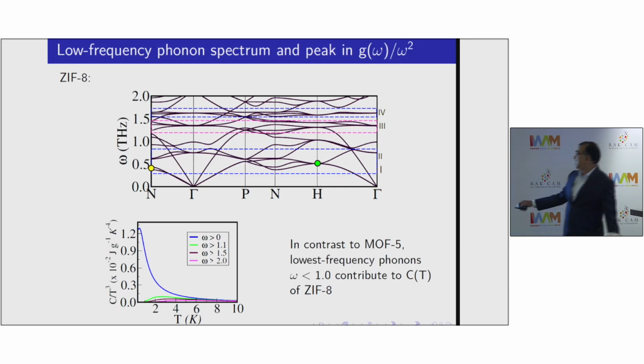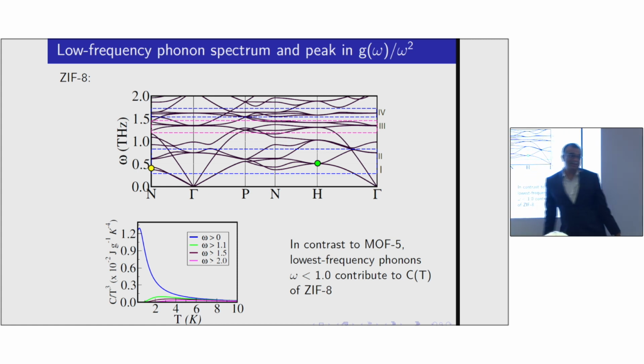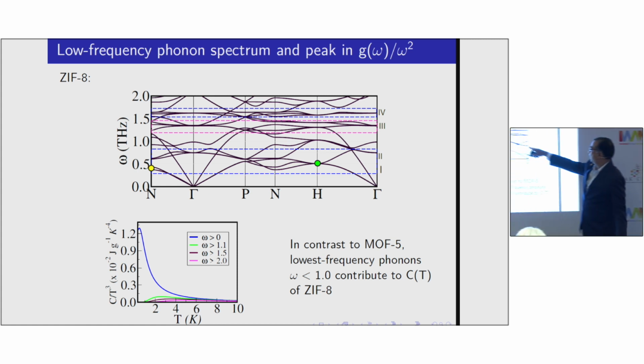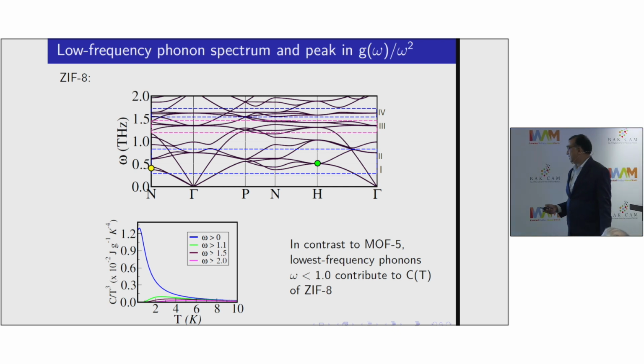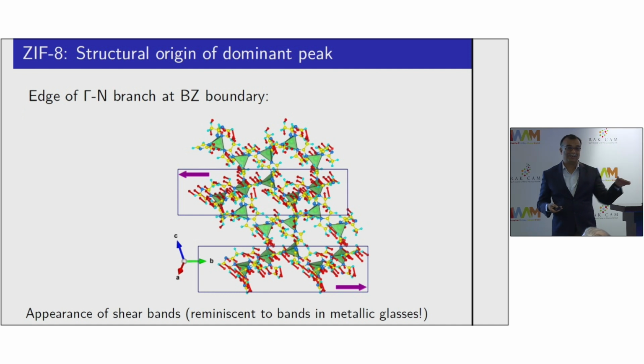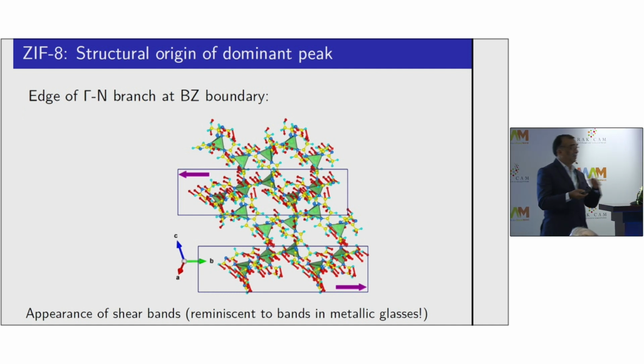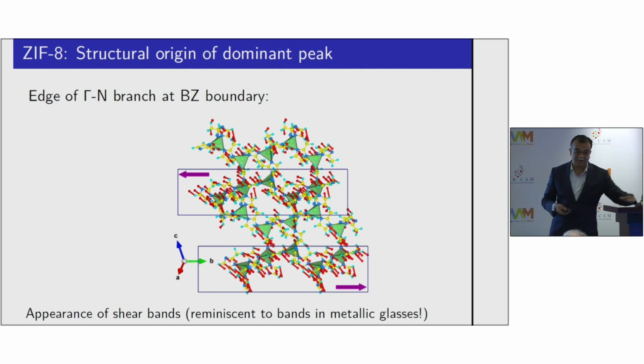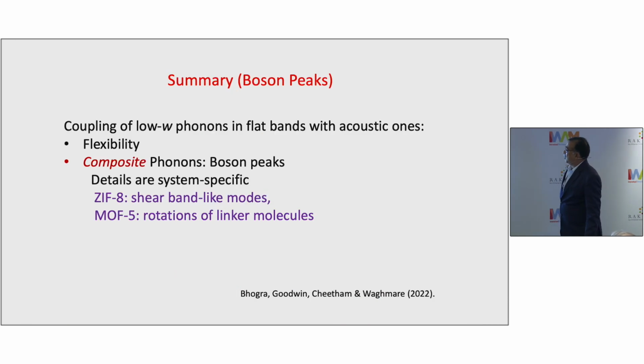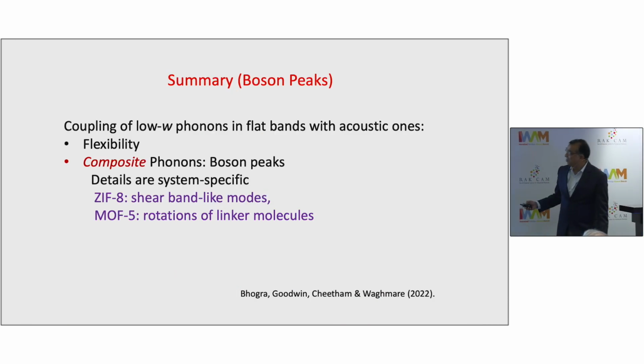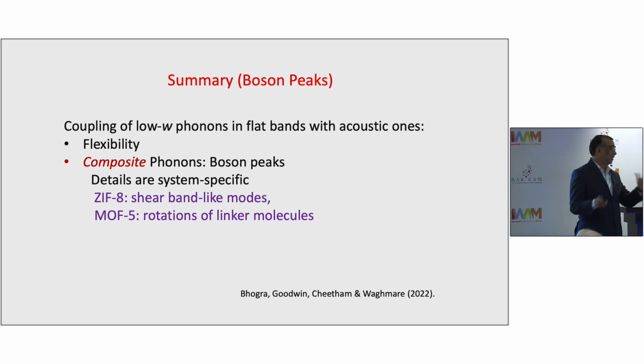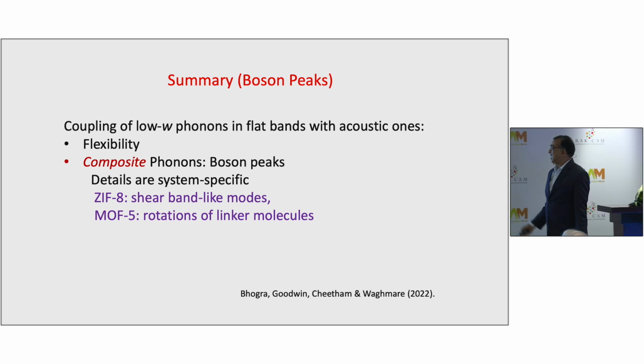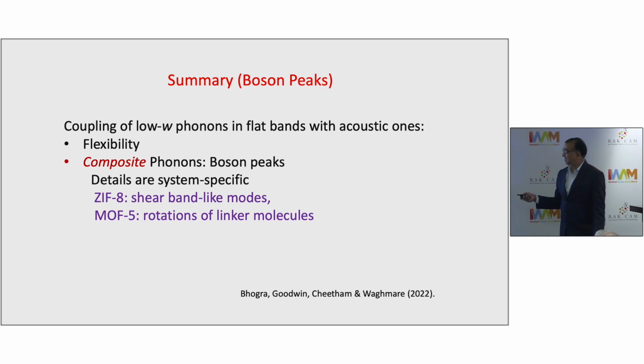In ZIF8, again, there's only one set of phonons which dominates the boson peak. And that set of phonons is indicated here in this window. And basically, those phonons involve shear band-like distortions. And again, this is something which is known in amorphous systems. They deform in response to external stresses by forming shear band-type structures. So let me summarize. It's the coupling between low-frequency optical phonons in flat bands with acoustic ones that gives rise to both flexibility and composite phonons. Meaning phonons are a combination of strain and internal strain waves. And the details are system specific. In ZIF8, these arise from shear band-like modes, whereas in MOF5, they involve rotations.